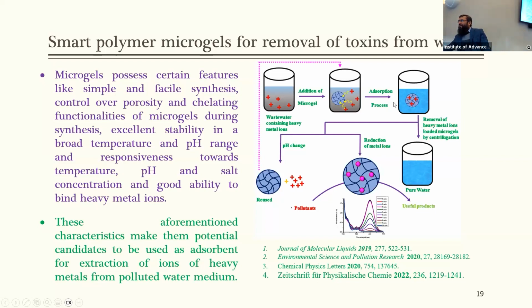So the recovered microgel system containing the metal ions can be treated in two different ways. We can remove the metal ions from the microgel system by changing the pH of the medium, and we can reuse the polymer microgel system as an adsorbent again in the next cycle. Another approach is that we can reduce the metal ions into metal nanoparticles to obtain a hybrid microgel system, which can be used as a catalyst for degradation of organic dyes present in aqueous medium. We have reported both approaches in our different publications.